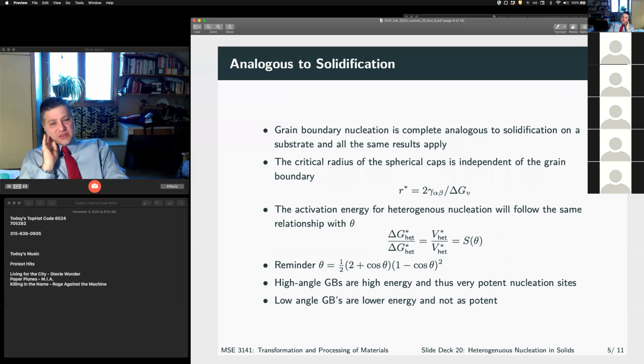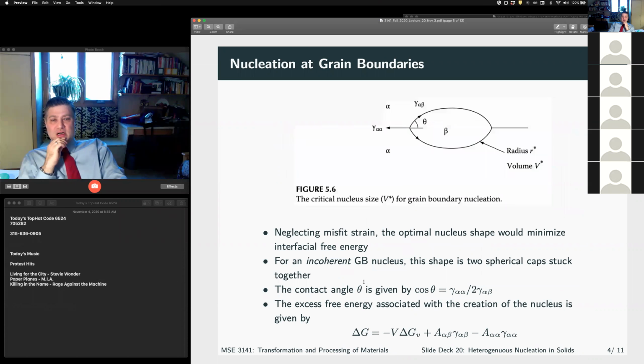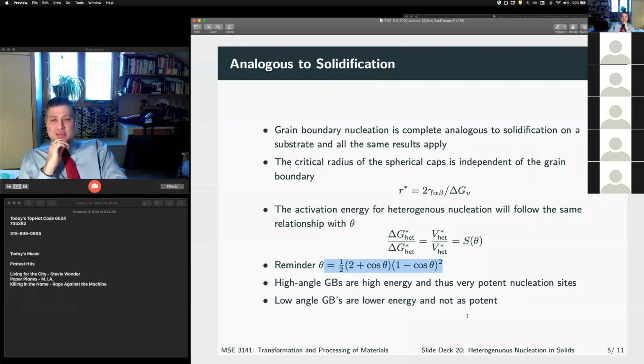We have the ratio between homogeneous to heterogeneous, which is given by our factor S of theta, right? Our theta term is the same, okay? So high angle grain boundaries, where I have a big orientation mismatch across this, are very high energy. So they serve as potent nucleation sites. Low angle boundaries and special interfaces like twins are lower in energy, so there won't be as much nucleation happening on them. They're not as potent nucleation sites, right?